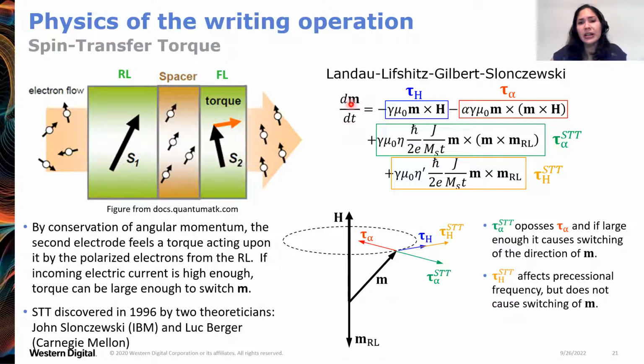I'm showing here the Landau-Lifshitz-Gilbert-Slonczewski equation describing the precessional motion of this magnetization about the effective applied magnetic field. What I want to point out here is that this green term, the spin transfer torque term that is going to flip the magnetization, is directly opposing this red term, the damping torque, that's acting to pull the magnetization back toward the applied field, back to equilibrium. For this reason, we want to engineer the free layer material to have a low damping constant alpha so that we can have the most efficient spin transfer torque to flip the magnetization.